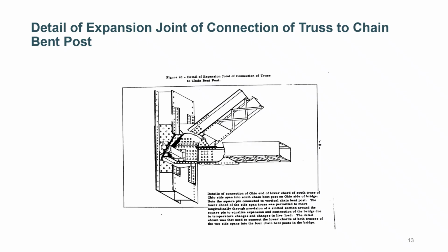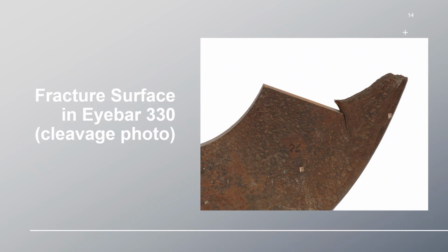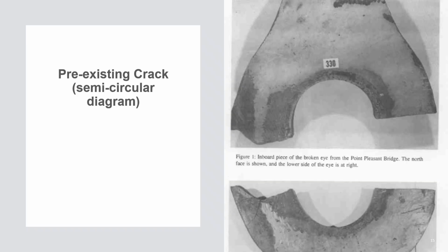However, this heat treatment resulted in elevated hardness and reduced ductility in thicker sections, yielding low fracture toughness at service temperatures. Consequently, the material exhibited brittle behavior once the crack reached a critical size, propagated via cleavage fracture under normal tensile stresses amplified by geometric concentrations at the eye head, and secondary effects such as joint rotations and traffic-induced vibrations.